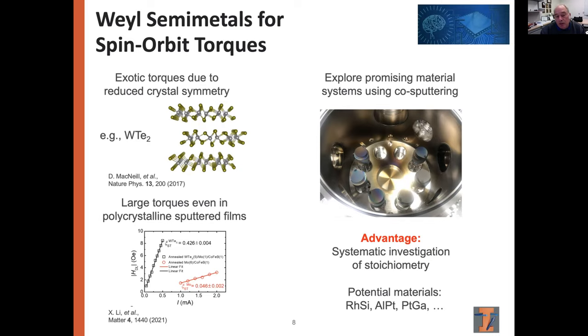So our goal is really to look at which Weyl semi-metals are good for this purpose. And for example, use the type of materials that will be explored as part of this proposal, like the ones that John mentioned using CVD, to then see what kind of spin transport properties we can expect from them. But in parallel, complementary to that, we have a deposition chamber using a confocal sputtering system that allows us to deposit various elements at the same time. And so that allows us also to explore in great detail how different compositions may give rise to different transport properties and spin transport properties.